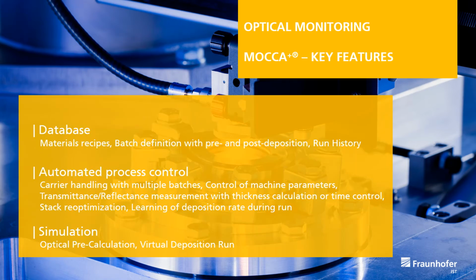MOCCA+ is not only designed for the optical monitoring, but also for the control of the whole deposition machine. We have the coating steps defined in material recipes inside the database. In this part is also the batch definition located, with details on machine preparation and the stack of single layers. The process control is able to do fully automated production, including substrate handling with pre-planned batches. It can do a stack re-optimization connected with OptiRay or OptiLayer.